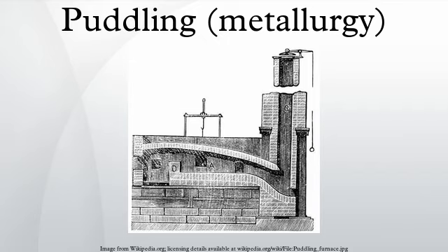This was invented by a puddler named Joseph Hall at Tipton. He began adding scrap iron to the charge. Later he tried adding iron scale. The result was spectacular in that the furnace boiled violently. This was a chemical reaction between the oxidized iron in the scale and the carbon dissolved in the pig iron. To his surprise, the resultant puddle ball produced good iron.